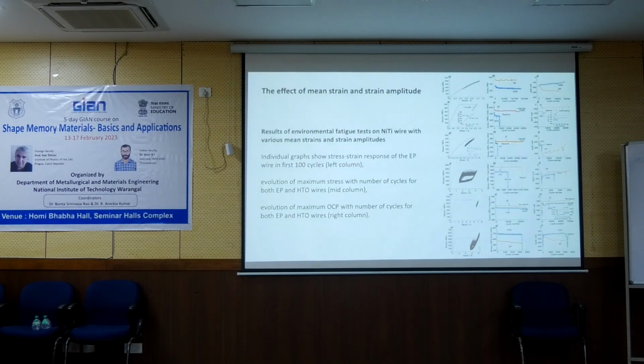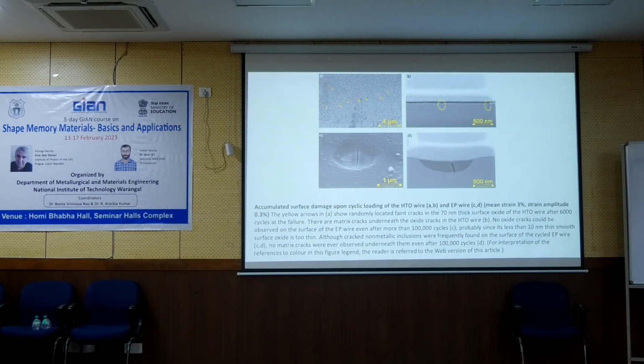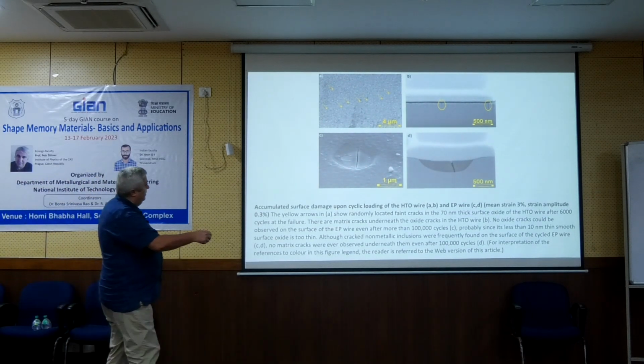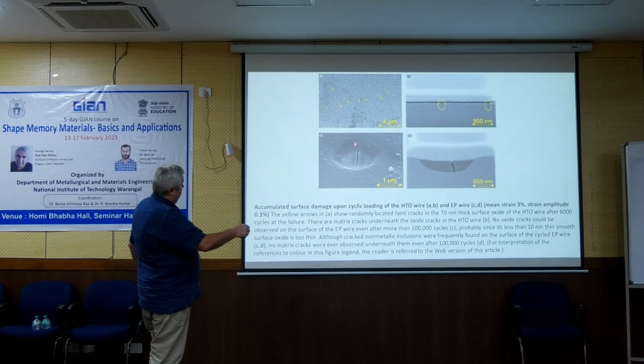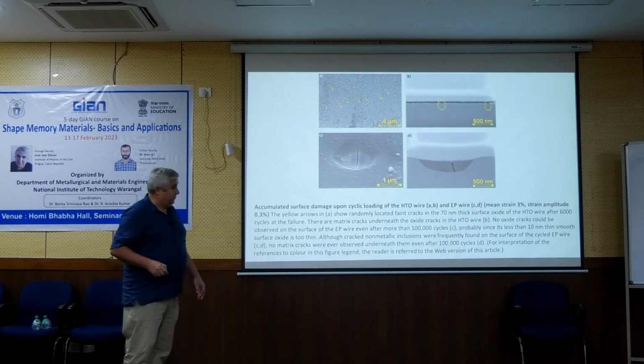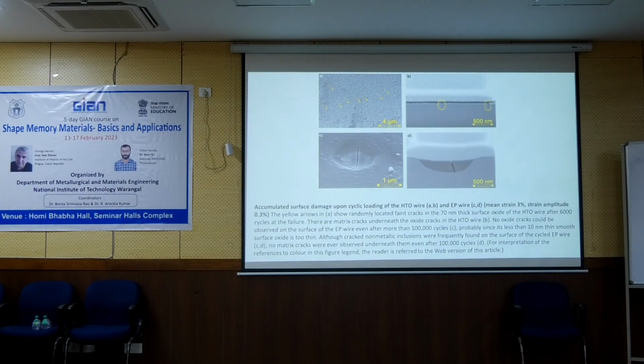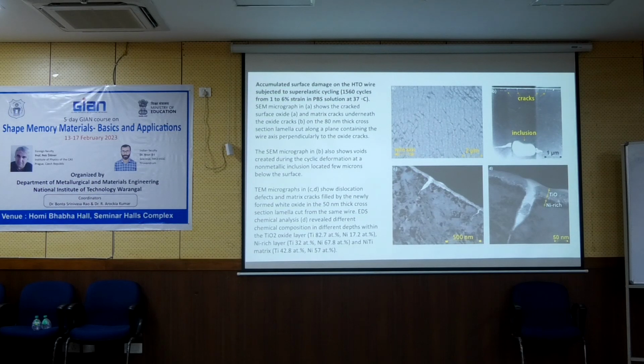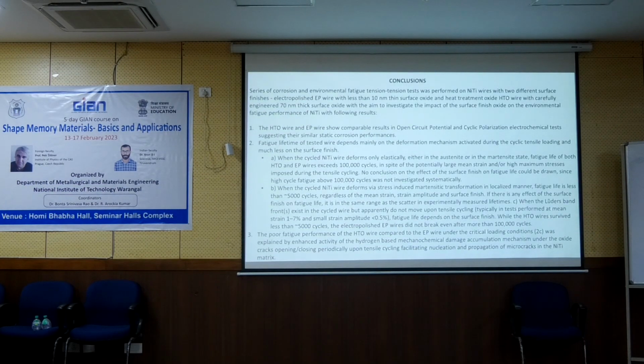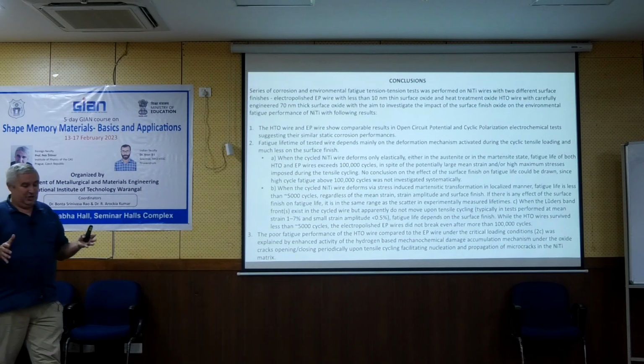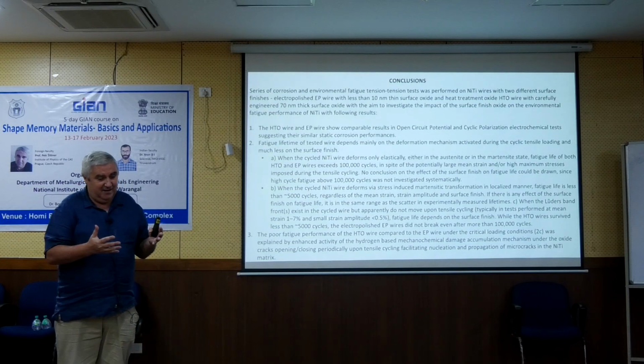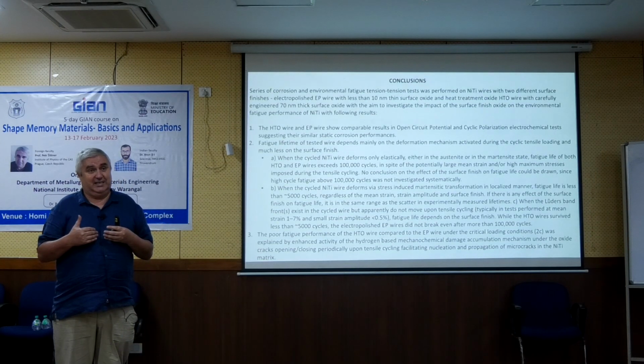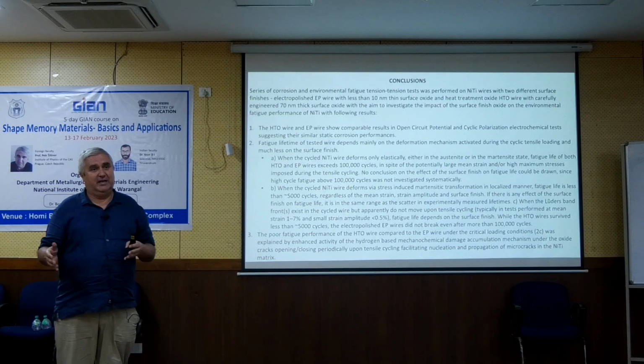Now, you can look at the article. You have the results here in the PPT slide, and this is an example of an oxide particle which typically cracks during the superelastic loading. You will see such cracks in the oxide, and this then causes the changes. But finally the conclusion is that the mechanism works here, and this special HTO wire is not a good solution for solving the fatigue problems. But overall you also have to assure good corrosion resistance in the static case, and then the HTO is much better than electropolish. So if you average, you find that the HTO is better than electropolished.